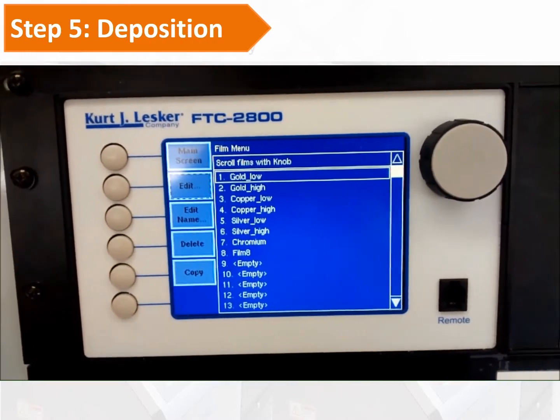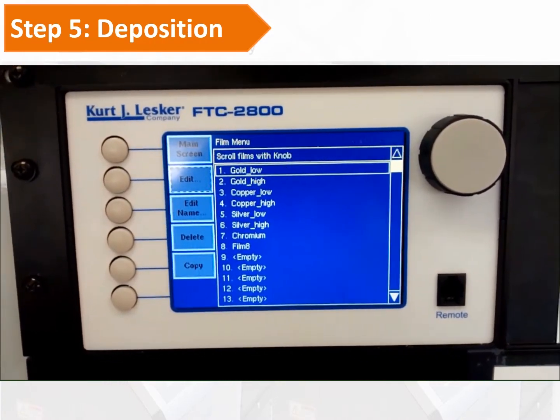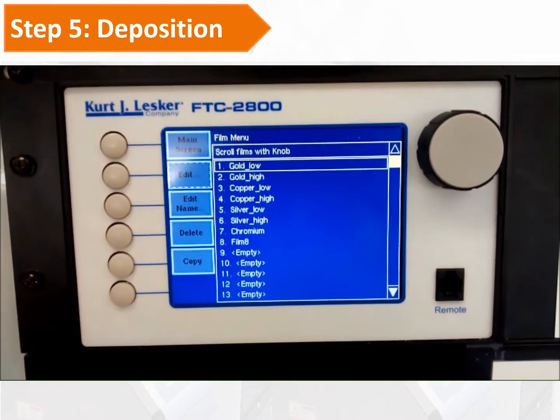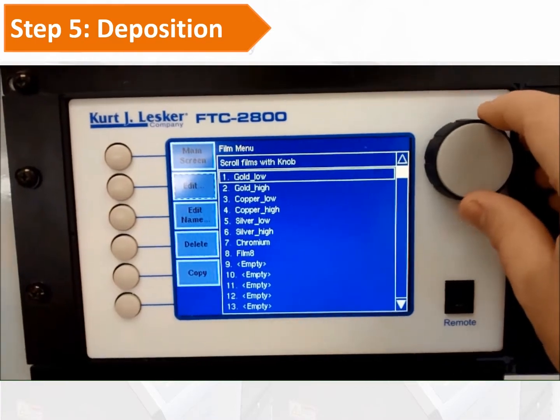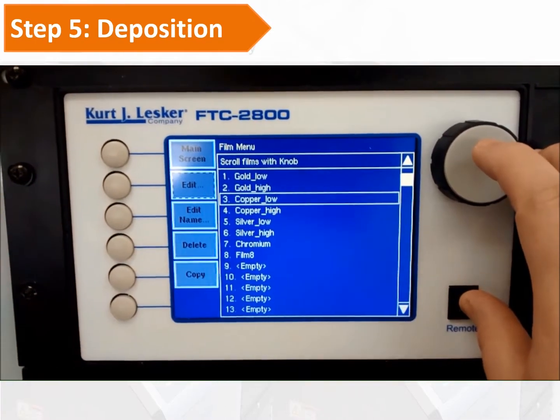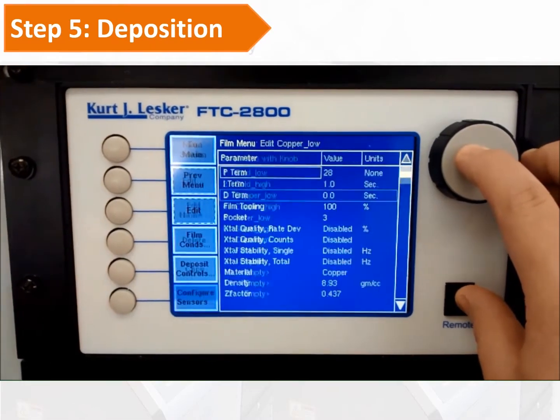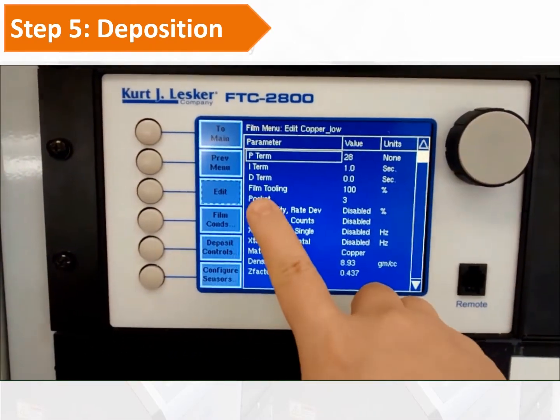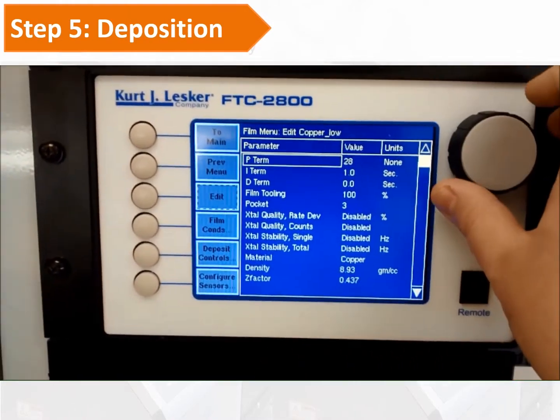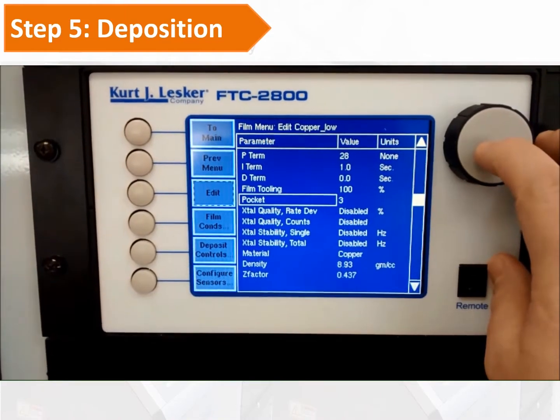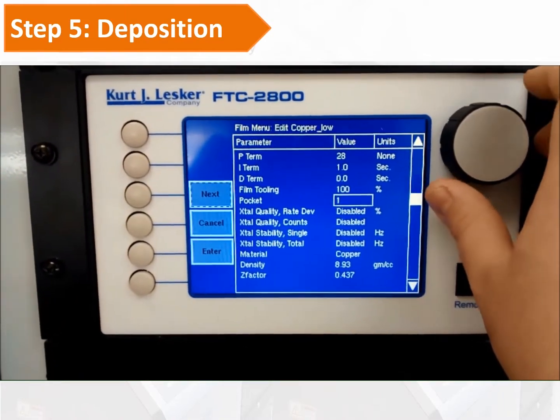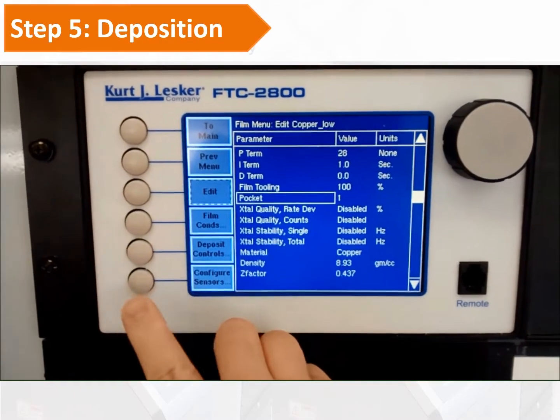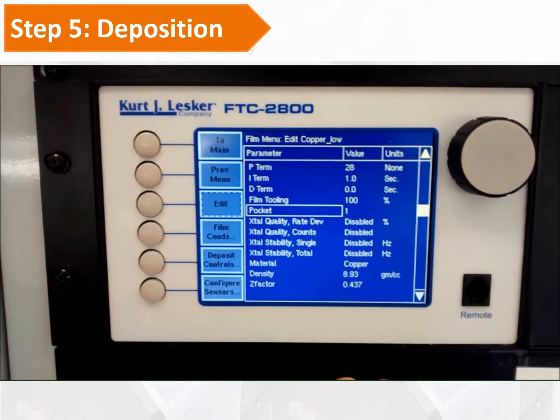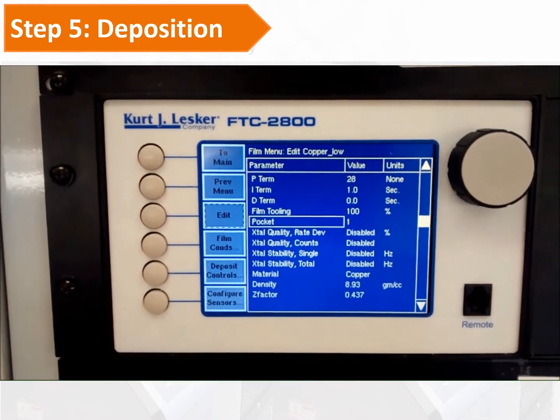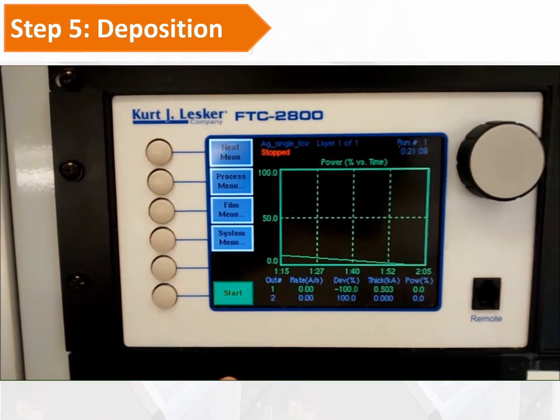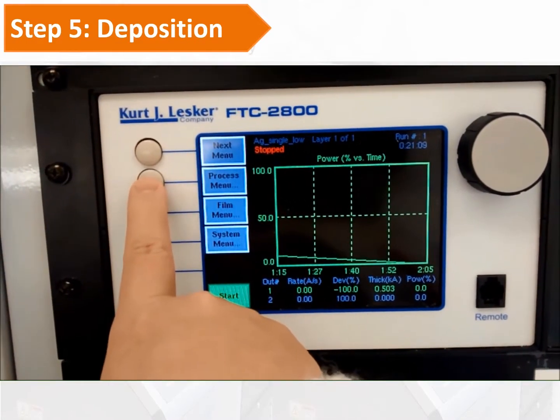So now we take the copper low recipe as an example. We rotate the wheel to copper low and press it. And now we can rotate to the pocket number. It's pocket 3. This time we loaded copper in pocket 1, so we change it back to pocket 1. And then we press enter here. When this number is ready, we can go back to the main screen, press to main, and then press the process menu.